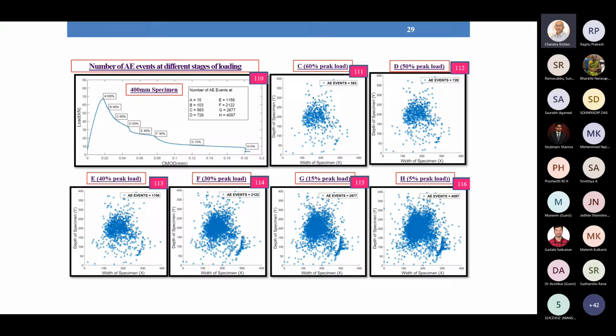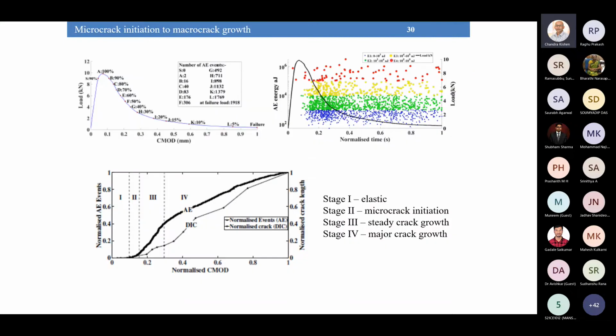And these failure criteria are applied to structures like dams and bridges, which are very large. Since concrete exhibits a strong size effect, we have to make a correction for those failure criteria. So the best way is to perform these tests on large specimens, as large as 1 meter by 1 meter, instead of a 150 millimeter cube. That is what we are planning to do. But these are the preliminary results. From the acoustic emission, we can see under direct tension how the evolution of micro cracks has taken place. We are still working on this. And what we see is the number of events.